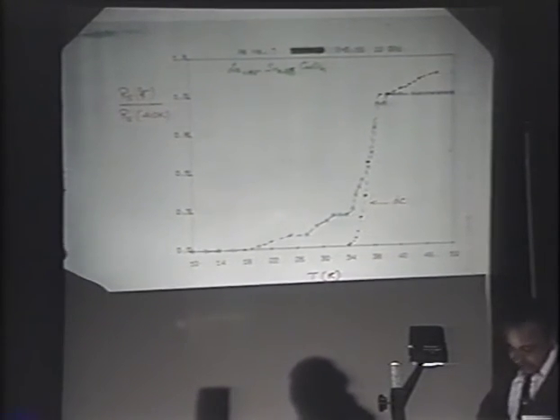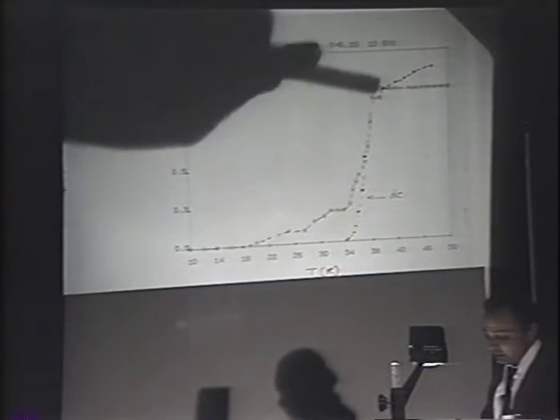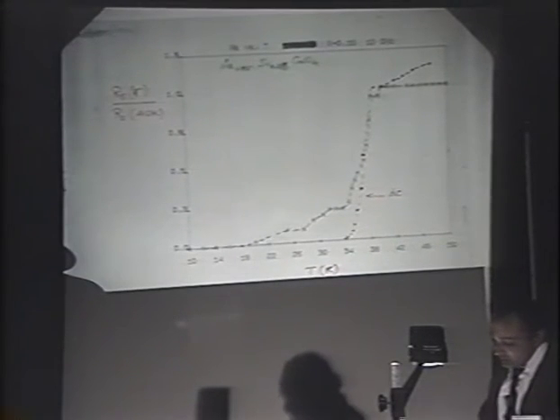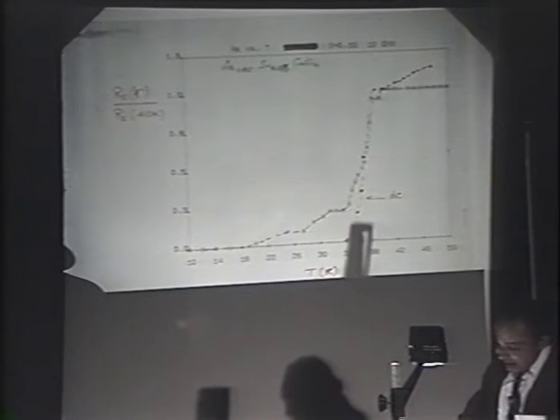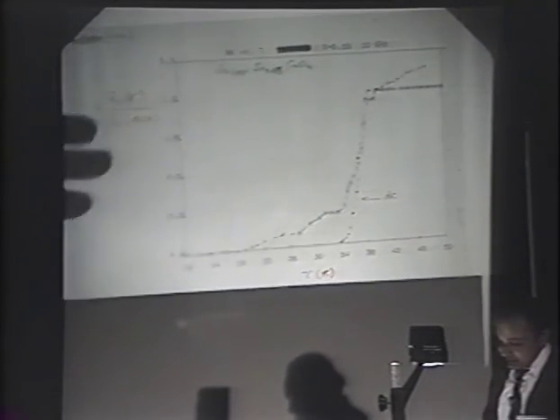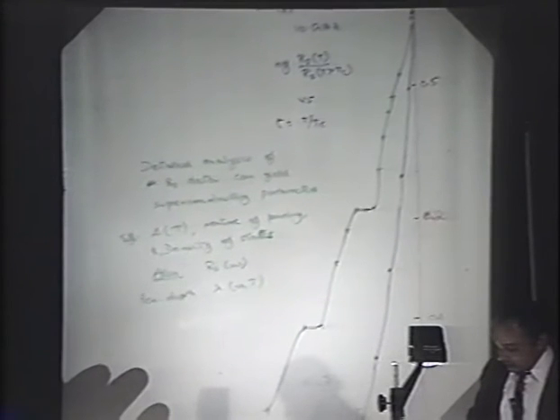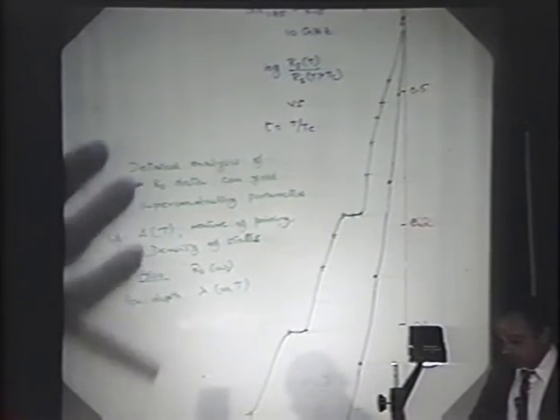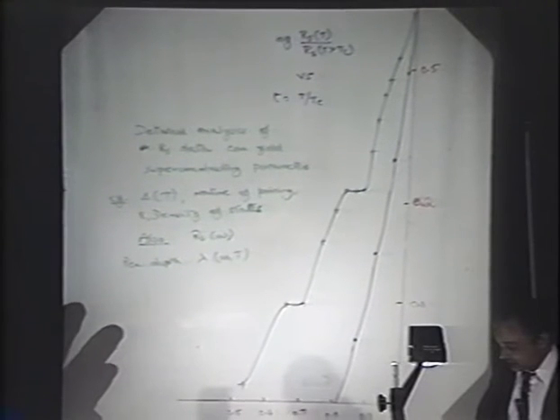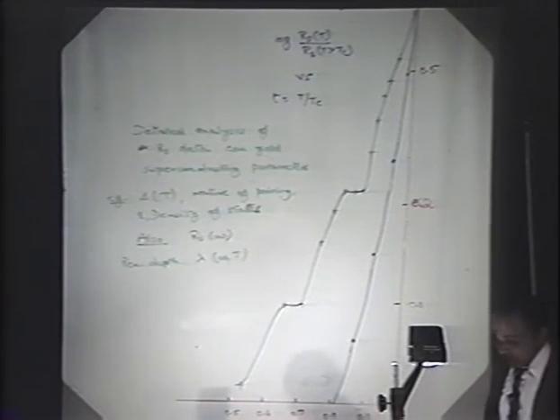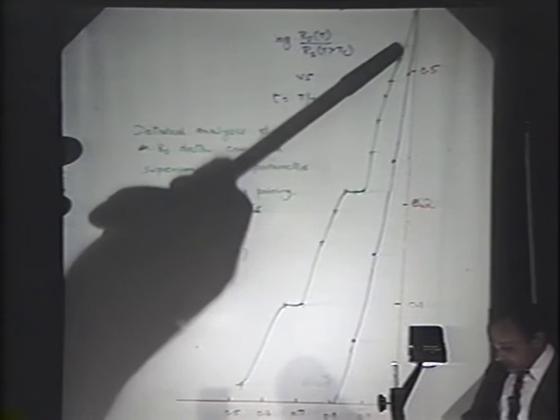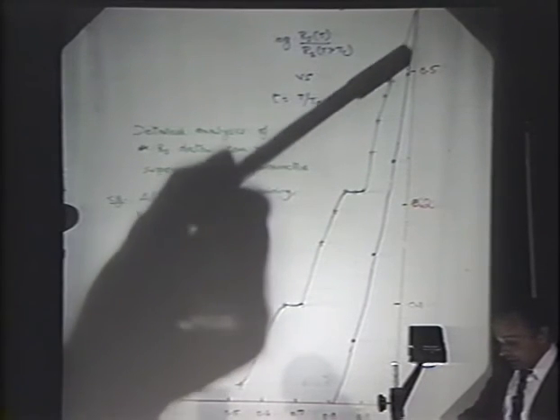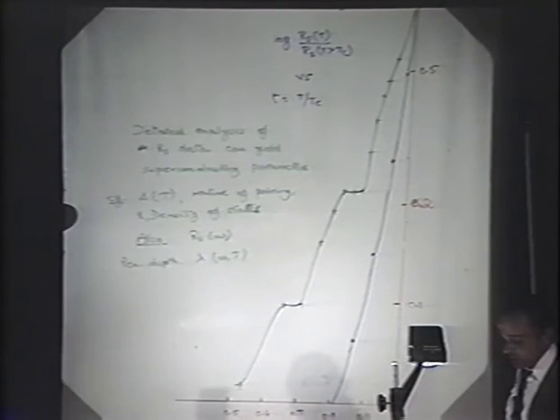Also shown on this plot is the DC behavior on the red dotted line here. Now let me contrast this on the next plot with the measurements on tin again. This is now a logarithmic scale versus reduced temperature, whereas the previous one was on absolute temperature. And the standard BCS material measured in the same configuration looks like this, and the theoretical line just passes through the points.